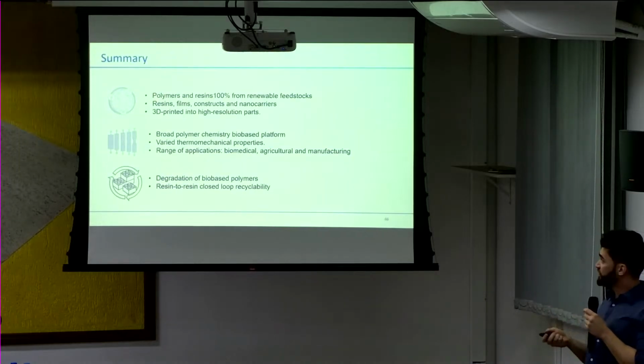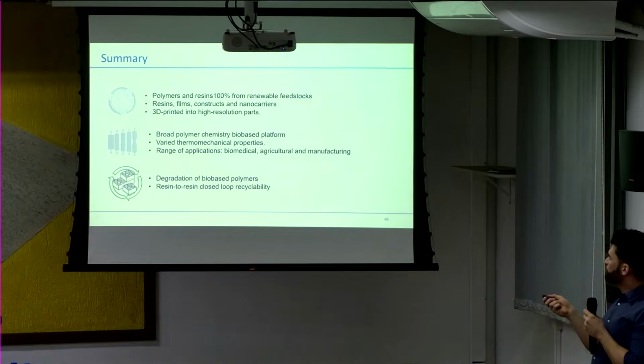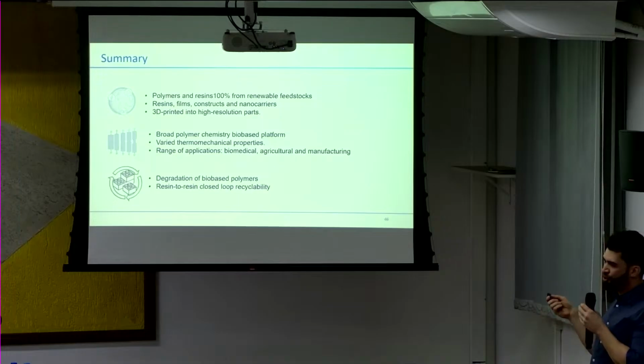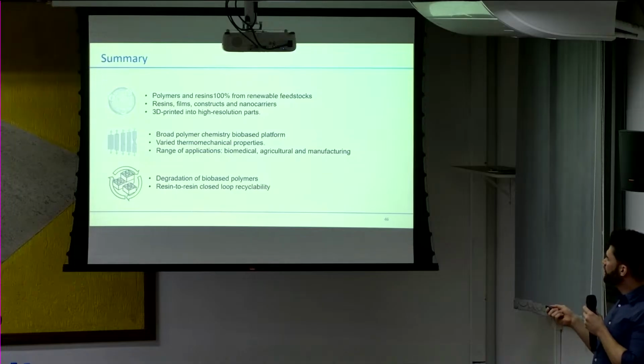As a summary of this talk, I've presented some polymers and resins, 100% from renewable feedstocks, used to make films, resins, constructs, and nanocarriers. The resins were 3D printed into high-resolution parts. I also showed a broad bio-based polymer chemistry platform with varied properties for several applications, and also showed the degradation of bio-based polymers and the closed-loop recyclability of networks.